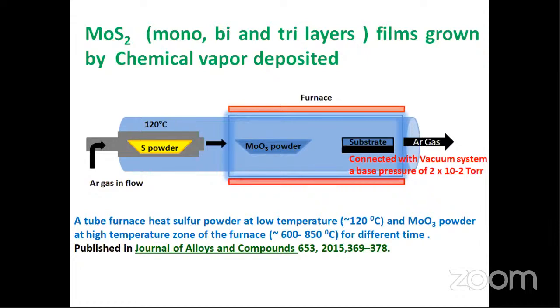Most importantly, we did a lot of experiments for this. We selected different amounts of sulfur, different amounts of MoO3 powder, and different temperatures. We selected a sulfur amount of 0.2 gram to 0.3 gram, and MoO3 powder amount of 0.2 gram to 0.4 gram, and temperatures of 600, 650, 750, 850, and so on. So there are several parameters we have selected here. Finally, with the help of these parameters, we have found different layers of MoS2.